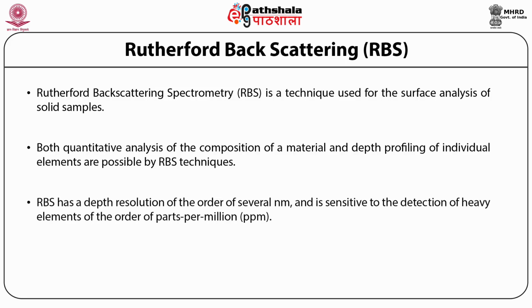The RBS has a depth resolution of the order of several nanometers and is sensitive to the detection of heavy elements in the order of parts per million.